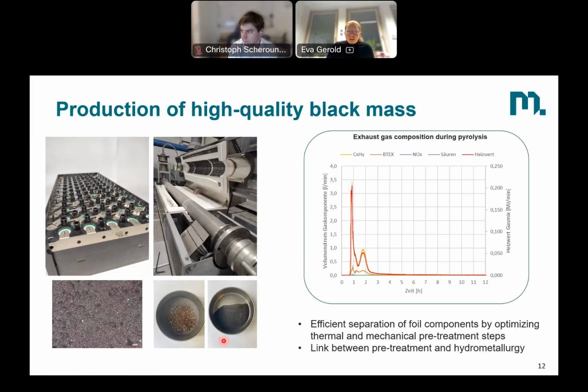Here is just a very short view on the thermal pre-treatment that is also studied at our university. So here we have a rotary kiln for pyrolysis. We take these batteries, we discharge them, we shred them, and then we go to a thermal decomposition. And what we can see is that we have quite a lot of different gases, but that we can have an efficient separation of the foils, and an efficient separation of the organics. But of course, there are some pyrolysis residues we also need to deal with.